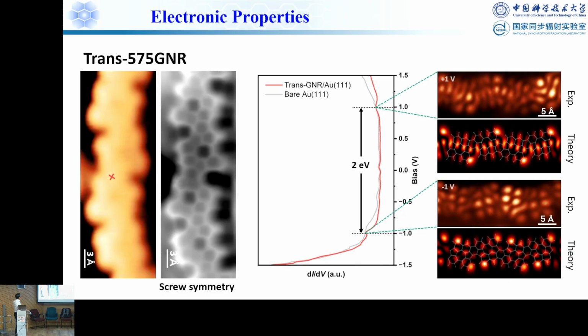nc-AFM with a CO tip. So it can really show that this is the trans structure which I showed before. With the STS measurement, it shows that this band gap is like 2.0 eV, and this corresponds to HOMO, and then if you do this state mapping, you can see that they do have this electronic state there, and this is quite consistent with the DFT calculated results.